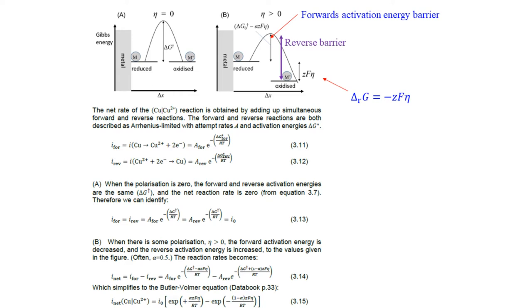Now, for this case of the polarization being zero, we can write down equation 3.13. We know that there is zero net rate of corrosion when the polarization is zero because there is zero net driving force. So we know that the I forwards, the forwards process current density, is equal to the backwards current density. So we can learn that those Arrhenius-modeled terms from equations 3.11 and 3.12 must be equal to each other and equal to the exchange current density when the forwards and backwards activation energy is considered to have the same value. That is something which we will now use in order to see what happens when we have case B in the diagram, when the polarization is positive.